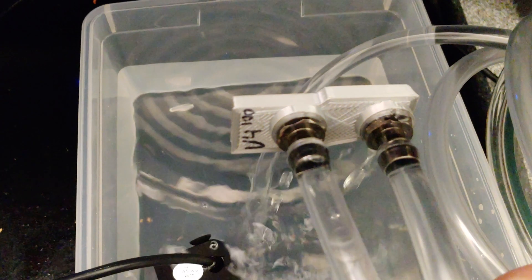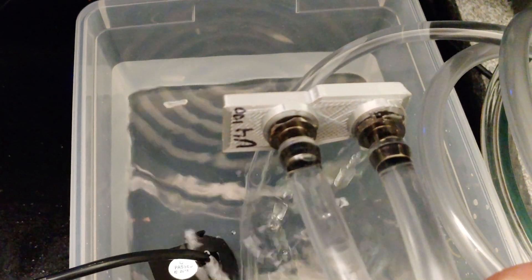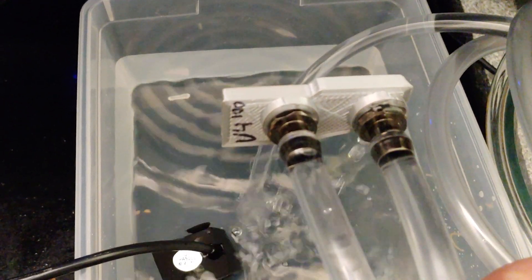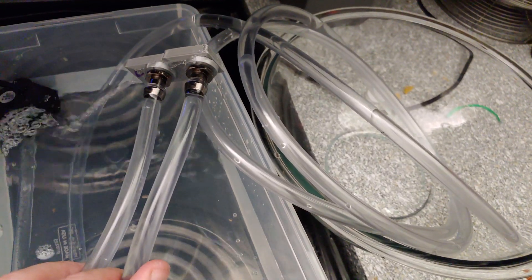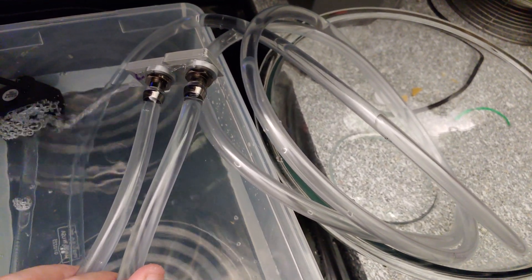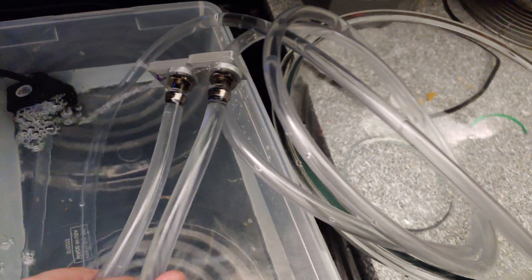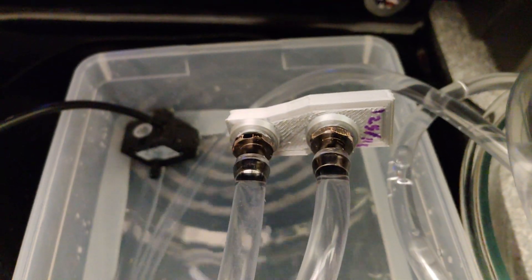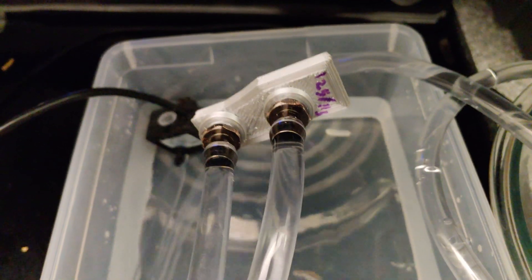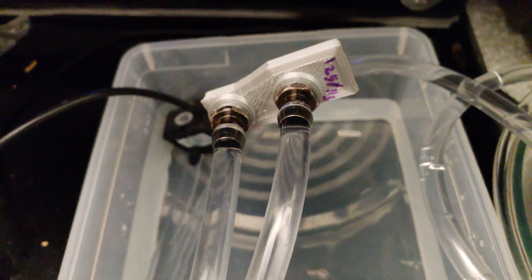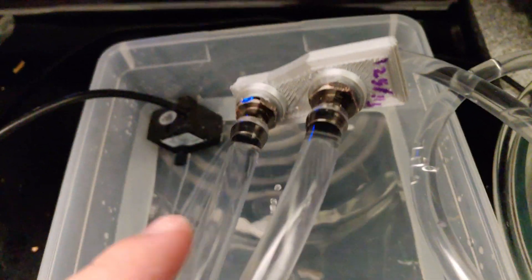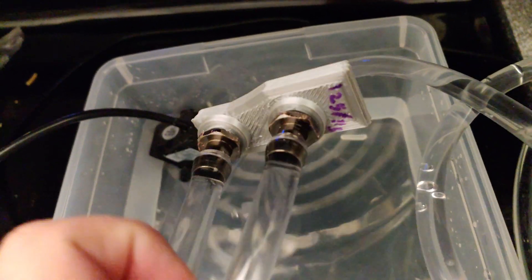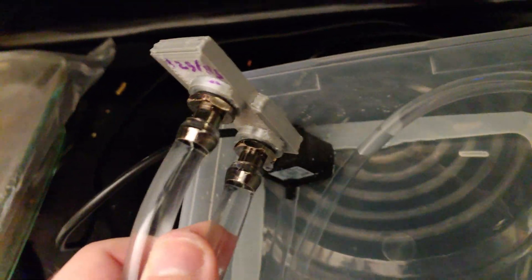Starting with 100% extrusion, we can see that we leaked a lot at the barb fittings. The 110% extrusion failed a lot more significantly and still leaked at the barb fittings. 125% extrusion wasn't as bad, still leaking at one of the fittings in particular, and we actually had a little leak here in the bottom corner.